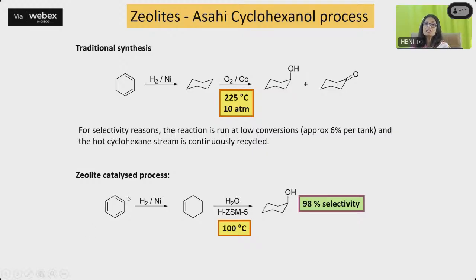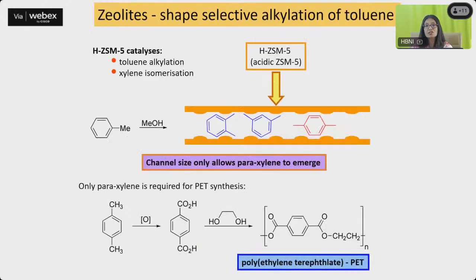But when you use zeolites to synthesize the same product, what is happening? The first step goes in a similar manner: you do hydrogenation in the presence of nickel, and you get this particular product. But after this, if you use zeolite as a catalyst, the reaction proceeds at only 100 degrees centigrade, and you get cyclohexanol with almost 98% selectivity. So this is how zeolites are being used.